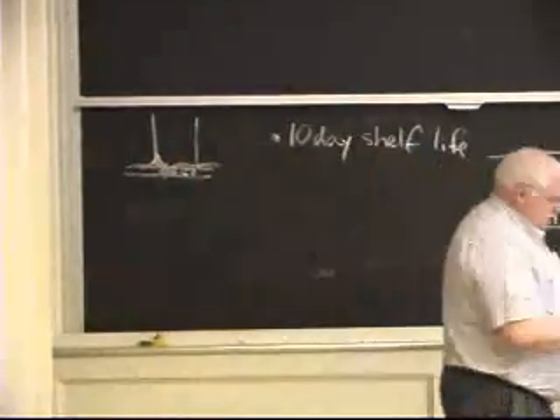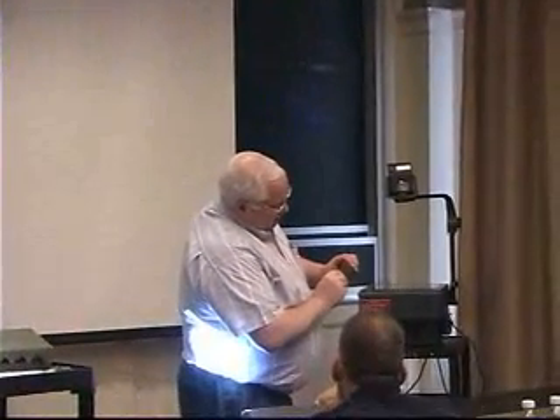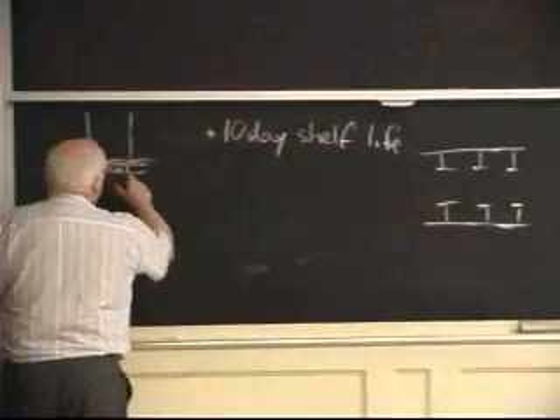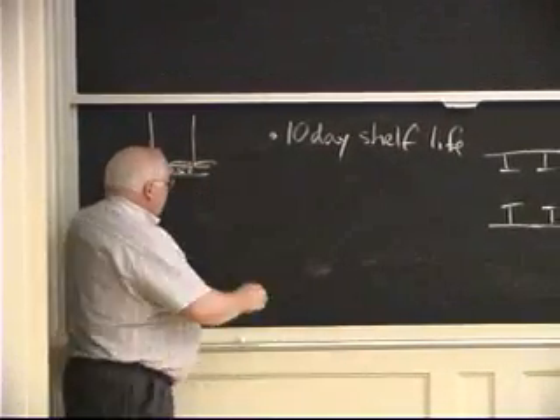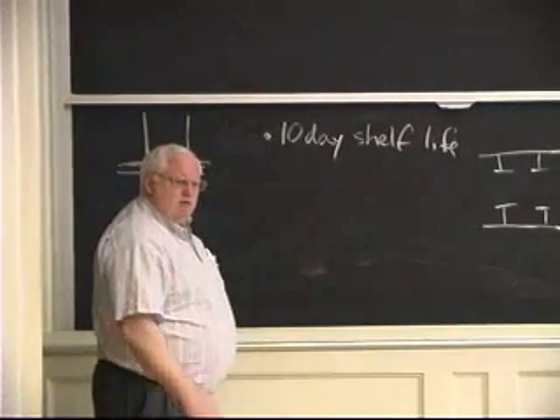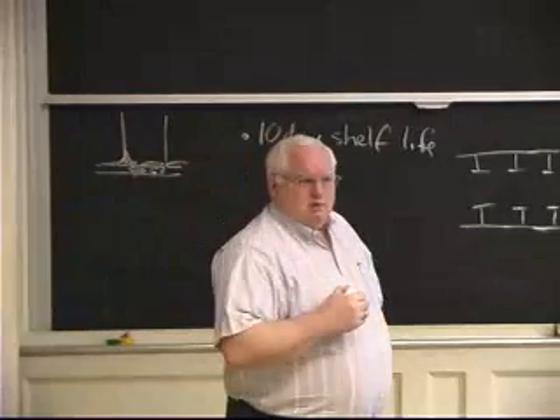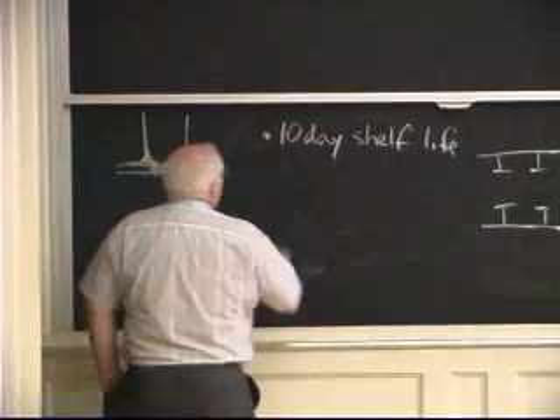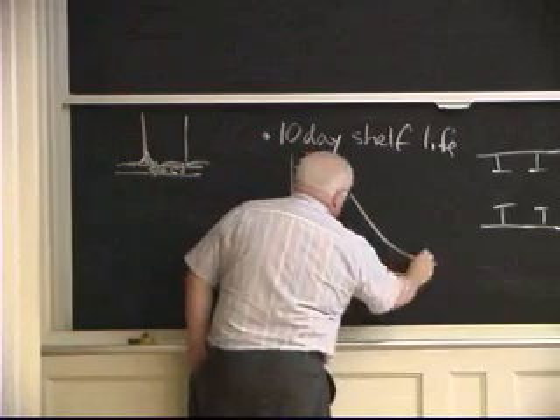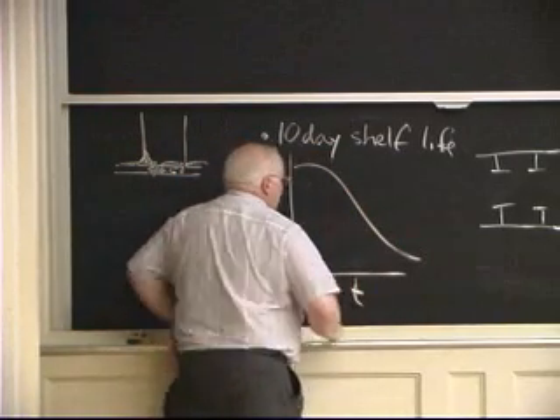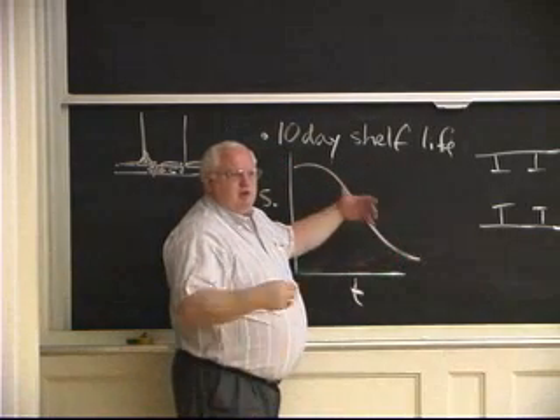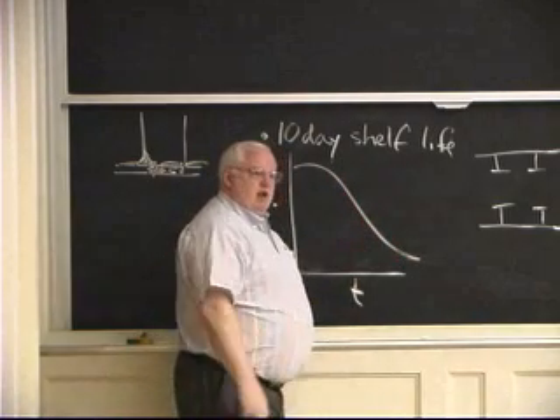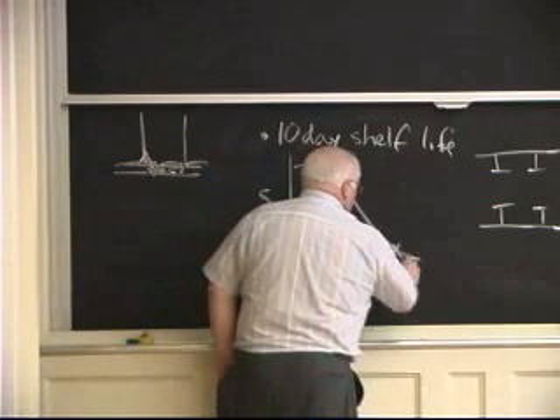And if you look on the end of this thing, you'll see a little layer, different color layer of adhesive right there between the graphite and the brown Hexcel foam. And you'll see that you don't have a nice fillet that formed in here. You got a lousy fillet, and it turns out they went back to find out, and lo and behold, they went back to 3M and said, you said it had a 10-day shelf life, and they put all these together in 3 to 7 days, which is well within the 10-day shelf life. And 3M says, oh, well, yeah, we say a 10-day shelf life. Here's the graph. This is strength of the adhesive versus time, and you lose strength as the stuff hardens up and doesn't flow, doesn't give you good wettability. And that's where 10 days is, folks, at the 10% strength level.